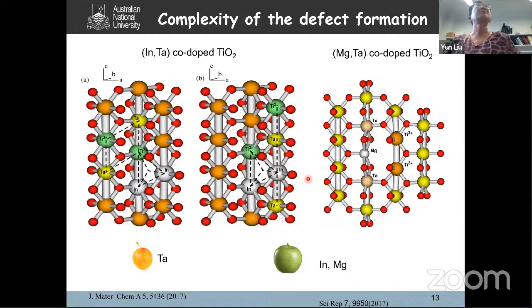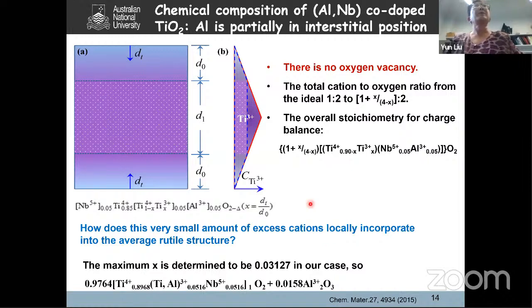This kind of defect formation is very complicated. For example, if we change the titanium, they get a different structure, and you also have a vacancy as well. And then if using magnesium as the dopant, you have this kind of structure. So in other cases, we always have difficult to dope ions. But the complexity of this strategy is also present here.